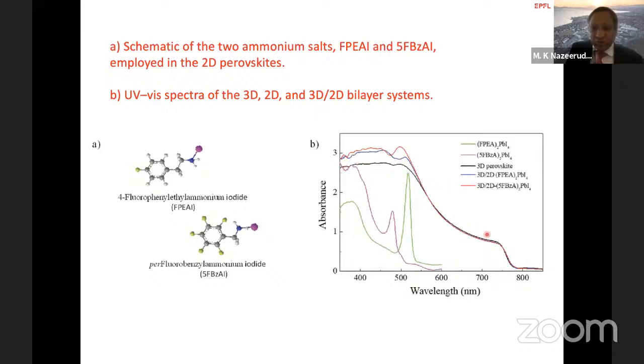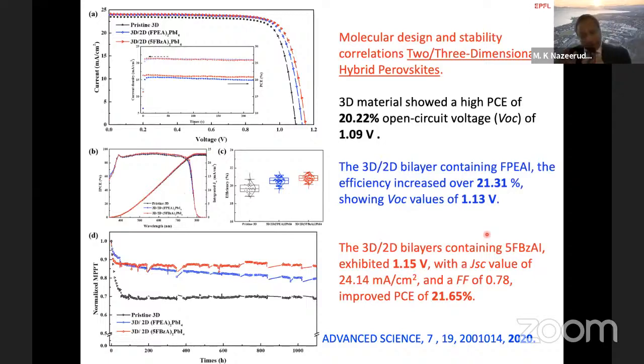The data are shown here. Now, without going into the characterization details as before, let's go directly to the PV data. So as a reference sample, pure three-dimensional perovskite, focus on the VOC, that's 1.09 volts, that's the black line. Now, after depositing the fluorobenzylamine as a two-dimensional perovskite cation, if you look at the VOC, it increased from 1.09 to 1.13, that's the blue color, that's the IV characteristic shown here. Now going from the fluoro to pentafluorobenzylamine, the VOC has increased from 1.09 to 1.15.